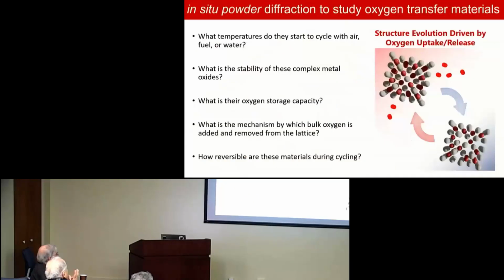What we've been doing is in situ powder diffraction to study oxygen transfer in these materials using both synchrotron X-rays and spallation source neutrons, and thinking about answering questions like oxygen storage capacity. So these are materials not really for storing oxygen. Oxygen is easy to store. It's more about using these materials instead of oxygen from the atmosphere for particular applications. There are many metal oxides that are very reversible because they can support oxygen site defects or vacancies and easily cycle back and forth.